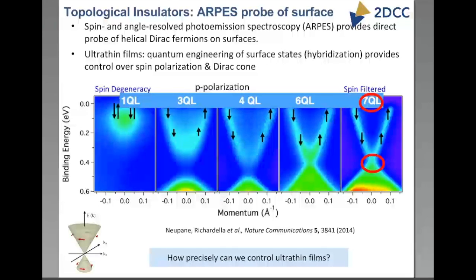And it shows you how the band structure changes as you go from 7 nanometers down to the ultra thin limit. And what you see is that at 7 quintuple layers or 7 nanometers, you get a Dirac cone. As you start making the sample thinner and thinner, the Dirac point is disrupted, and eventually a gap opens up. So this tells you that there's a quantum engineering possible of the surface states. This occurs because of hybridization, and it gives you control over spin polarization in the Dirac cone physics. And so from an MBE grower's viewpoint, the key aspect here is how precisely can we control these ultra-thin films.